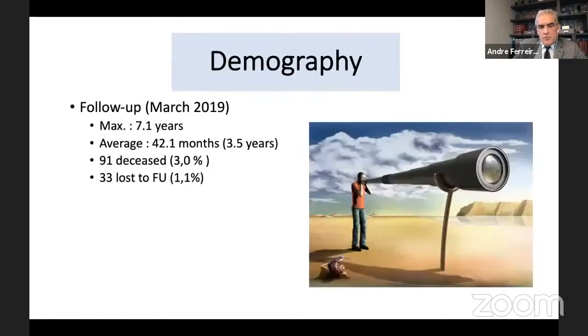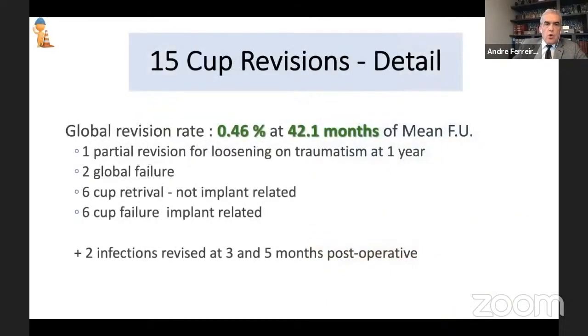So the demography is classical too, with 3% deceased and only 1% lost to follow-up. We have to face 15 cup revisions. Why? One partial revision for loosening on traumatism at 1 year, 2 global failures, stem and cup, 6 cup retrievals for not implant related reasons, and 6 implant related with 2 infections.